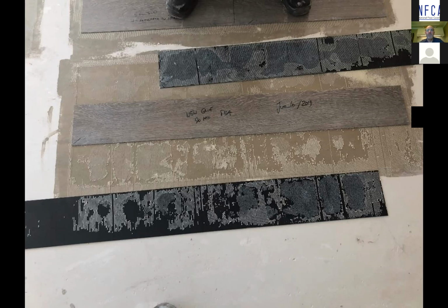You know, 24 hours is a little bit premature. You can get some adhesive qualities in 24 hours, but I would recommend if you're doing bond tests to give it 3 days, like do these on a Friday and then come back on Monday, and you'll have some pretty good strengths and some pretty good curing qualities. You don't have to wait 2 to 3 weeks to get good values, but at least 3 days gives you some pretty good values on these.